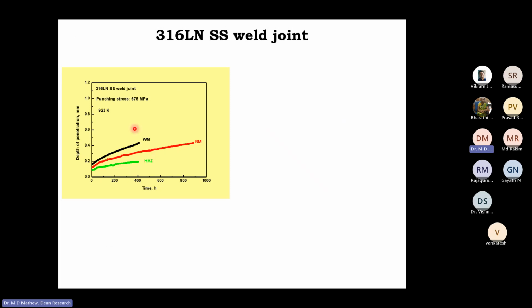This shows the creep curves of the 3 different microstructural regions. The top one is that of the weld metal, the middle one, the red one, is the base metal, and then this is the heat affected zone. So it turns out that in the 316 LN stainless steel welds, the weld metal is the weakest, and the heat affected zone is the strongest. But if you do similar tests in a ferritic steel, you will find that the heat affected zone is the weakest.